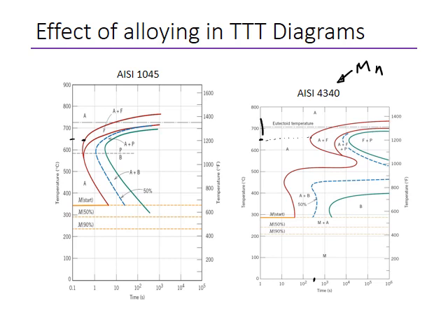So you can isothermally hold your material. Like let's say that you are quenching to this temperature and you are waiting for a very long time. So once you have all your material, the center of your material and the surface, at the same temperature, now you can quench and have a 100% martensitic structure rather than in this case.